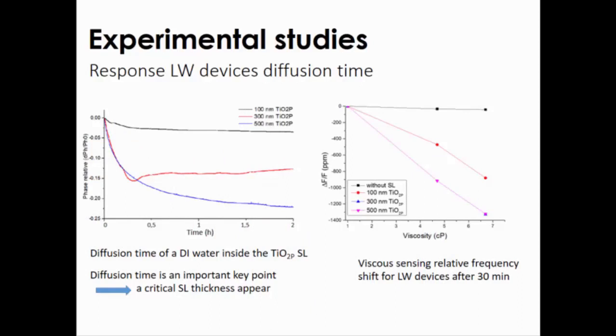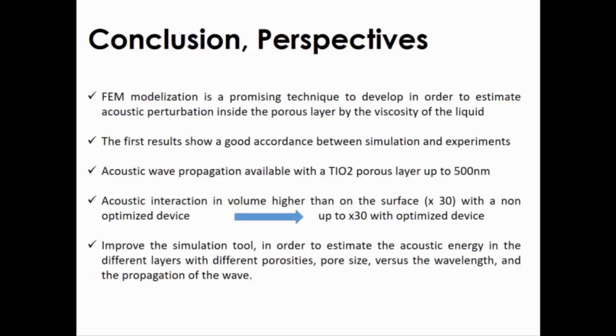These measurements are done after 30 minutes of exposition of the droplets inside the measurement cell. This could be a limitation of this kind of device because here we have three devices. If we want to have a stabilization for, for example, the 500 nanometer titanium dioxide porous layer, we have to wait two hours. It could be a limitation, but we can have a big increase of the sensitivity up to five after 30 minutes of exposition, to seven after one or two hours, and if we have a very optimized device, up to 30 or 50 more of sensitivity.